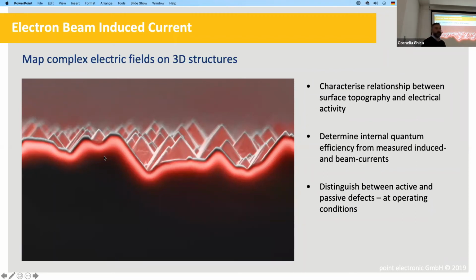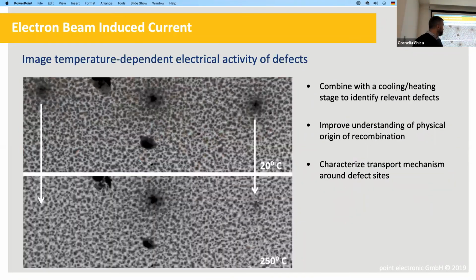And you can do this in the SEM on a large scale, and you can find sites of interest, defects, and so on. Another example would be in fundamental research, looking at levels in the band gap of where the defects are. So at which temperature does this recombination center switch on and off? It's proportional to where they are in the band gap. And this is an example on a solar cell again, and it's textured, so that's why we see these pyramids.